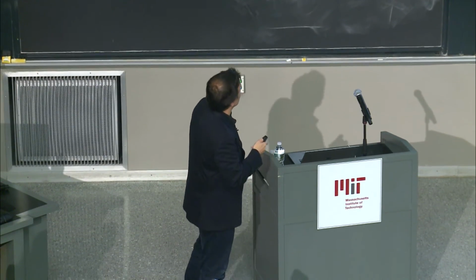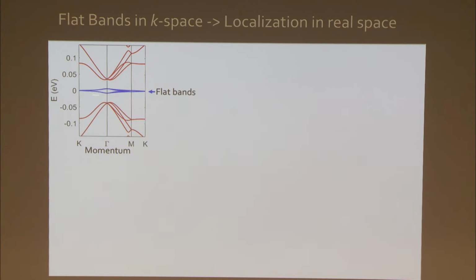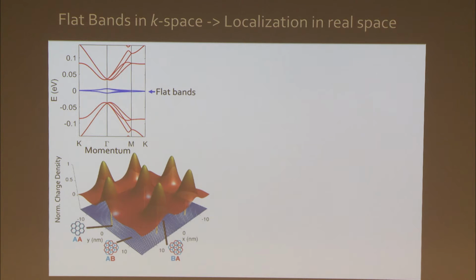The velocity of the electrons is many orders of magnitude smaller than the velocity in the original graphene sheets. Now, if we populate this flat band with electrons, flat in momentum space, and we want to see where those electrons go in real space, we have to do a Fourier transform to go from momentum space to real space, and the Fourier transform of a very extended flat object is a highly peaked object. So if you calculate where the electrons like to be when you place them in this flat band, it turns out they like to accumulate in certain regions in real space, which we call regions of AA stacking, where locally all of the carbon atoms in one sheet are on top of the atoms in the other sheet.